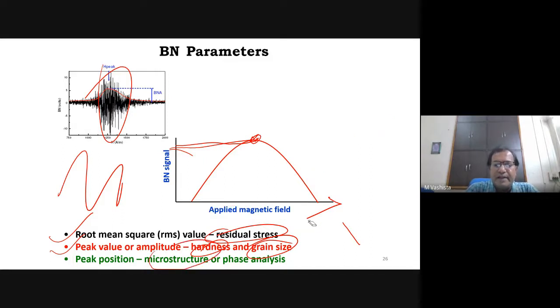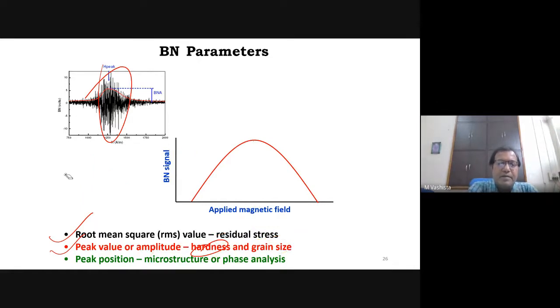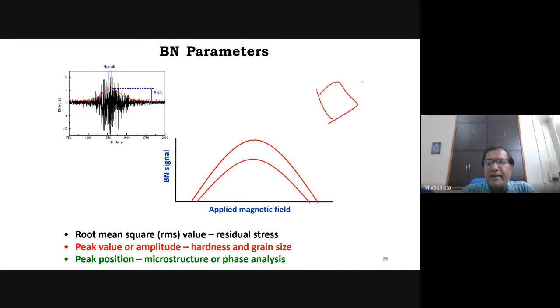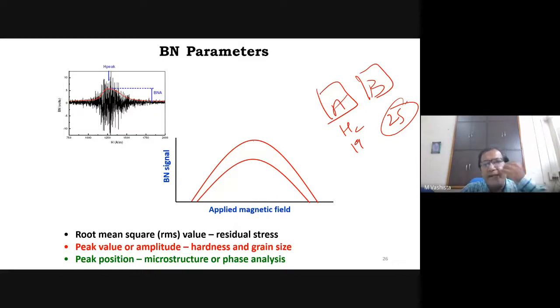I am considering two examples. Suppose I have two components, one component is A, another component is B. Component A hardness is HC 19, suppose, and B's hardness is 25. So it has large hardness. Hardness means grain boundary, grain size. So it has more grain boundaries. Grain boundary means a hurdle to the motion of the domain wall. When there is more hurdle to the motion of the domain wall, the signal will reduce. So I will get a smaller signal if the hardness is more.